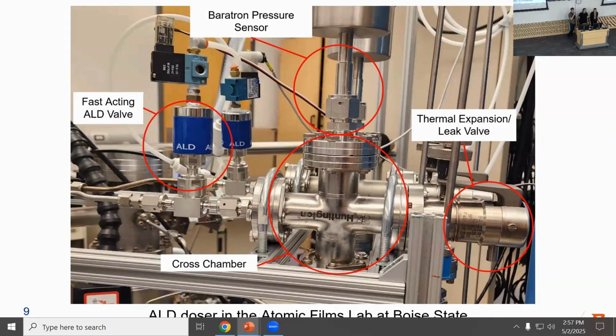On top of the chamber, there is a pressure sensor, so we can determine what that P is. And then on the left, there is a fast-acting ALD valve. This is a pneumatically controlled valve, and it opens very quickly and allows a short burst of nitrogen gas to go from the cross chamber into the main chamber. Regarding these variables that Sarah was talking about, the P refers to the pressure within the cross chamber, and that delta T refers to the time that the ALD valve is left open, and we call this the pulse time.